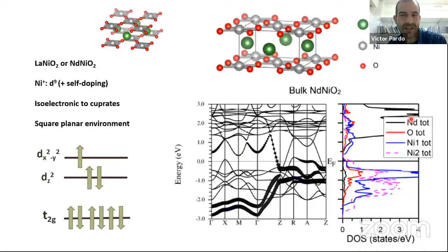So let's see what the electronic structure of neodymium nickel O2 is in a bit more detail. I presented to you in the beginning of the talk some electronic structure data in lanthanum nickel O2 by Warren Pickett and Anisimov, where they were saying that nickel plus is not copper 2+. The reason why they say it is that in this either neodymium or lanthanum nickel O2, you have these hugely dispersive bands that cross the Fermi level. So this has nothing to do with the prototypical electronic structure of the cuprates with just a single x squared minus y squared band around the Fermi level.